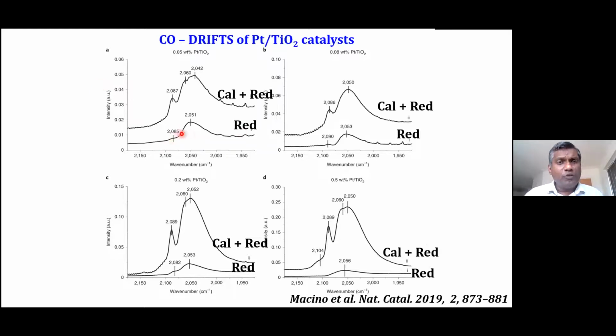As you can see, the reduced only catalyst, or let's start here, the calcined plus reduced catalyst adsorbs lots of CO. This is for 0.05 loading. For reduced only, it still adsorbs some amount of CO. If you take the other extreme, the intensity is much, much lower compared to, say, calcined plus reduced. That shows that in this case the platinum nanoparticle is more or less completely covered, whereas for 0.05 loading, for the same sort of heat treatment, platinum sites are still exposed.